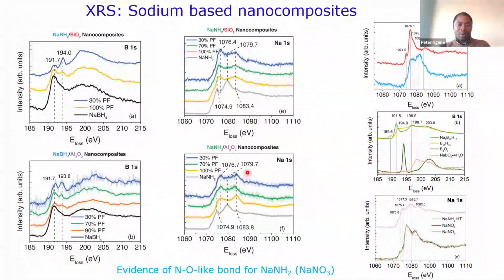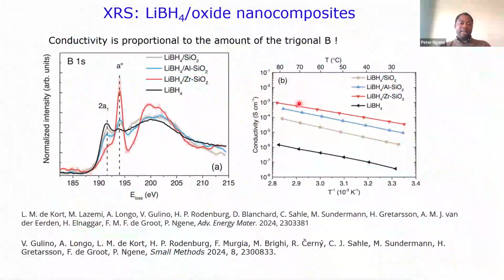You can see here, this is 1079.7, and we do see that's just a conclusion that we do have differences between these scaffold materials. An interesting thing is then that, okay, if this interface composition, which we're still trying to figure out the exact composition of, is actually true, then the concentration of this interface composition should scale with the conductivity of this